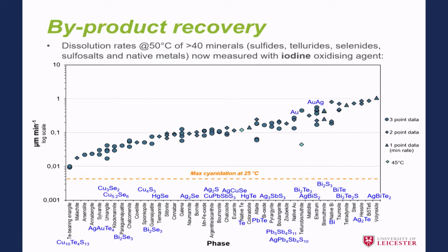Now most of these byproduct elements occur in rare, unusual minerals in your ores, minerals that you probably haven't heard of, most of these. Volynskite, for example. But we've taken all of these, we've looked at how rapidly they leach, and compared them to gold here and electrum here. And this is the cyanidation rate at the bottom. You can see that all of these minerals are leaching, and they're all leaching faster than cyanidation, so they're all potentially recoverable. But particularly over on the right, a lot of the bismuth and tellurium minerals are leaching as fast, if not faster than gold, whereas in the middle we have a lot of the antimony minerals, which we might also want to recover. So potentially we can recover these byproducts as well.